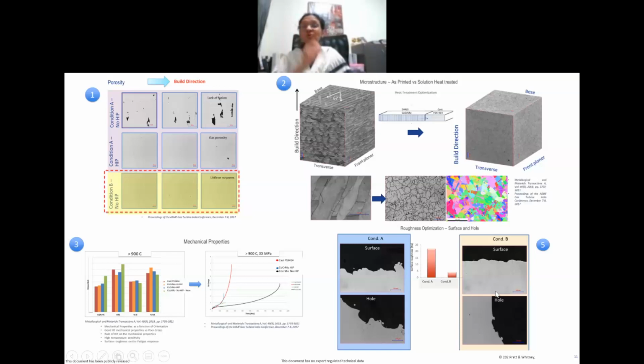What about the fine cooling holes, 0.2, 0.3 millimeter, 300 microns? How can I possibly know which cooling holes have a roughness like this? If you can see here, unmelted particles out here, a lack of fusion out here, and that will become a Kt factor, a stress concentration factor. Very, very difficult. So what we did is we partnered with our colleagues in aerospace here.